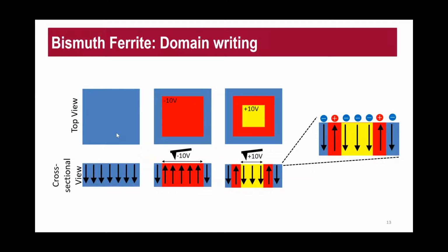So when you put this material under PFM and you apply, say, a negative 10 volts into a smaller region within the large region. Say the large region is 5 by 5. Now you are doing a domain writing by providing a negative 10 volts within the region 3 by 3. So you will see that this region will result in a contrast compared to the original view. And again, if you want to apply to a small region, say 1 by 1, typically positive 10 volts, this will also lead to a change in the polarization.